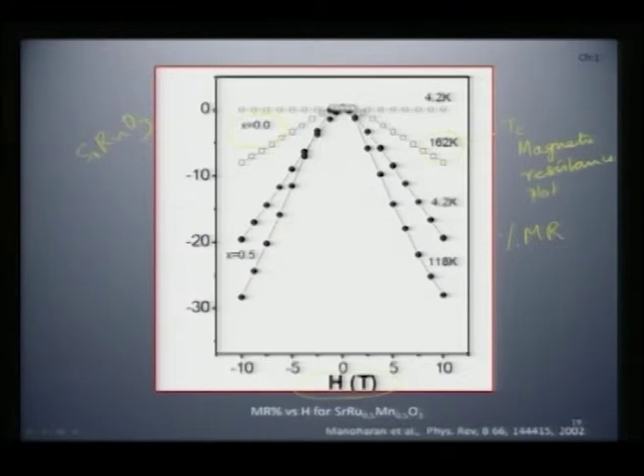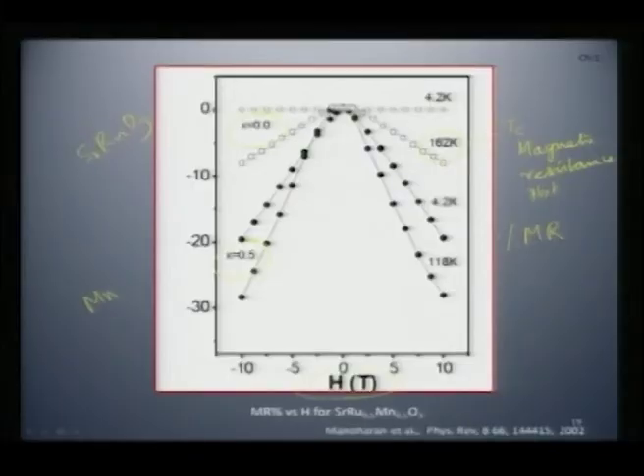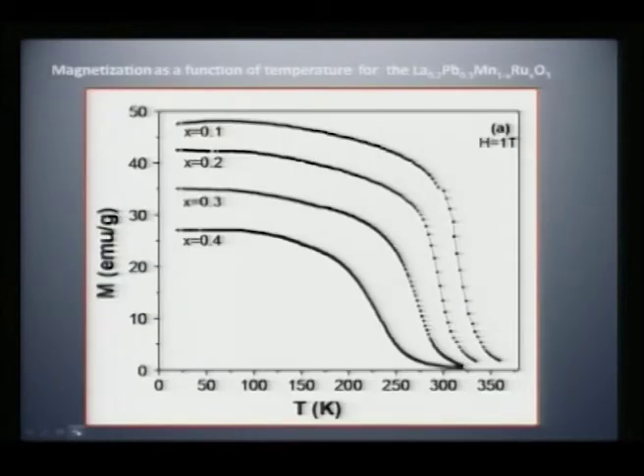it is still lower. Whereas in the case of SrRu0.5Mn0.5O3, you see there is almost 3 times the magnetoresistance compared to the parent compound. So there should be something unusual happening when you substitute manganese in the place of ruthenium compared to the parent oxide strontium ruthenate. We will see what exactly happens, and let me take you through another example also and